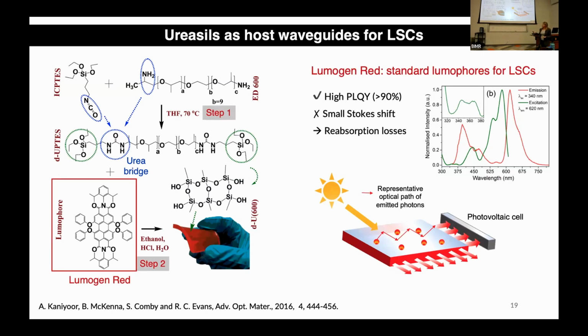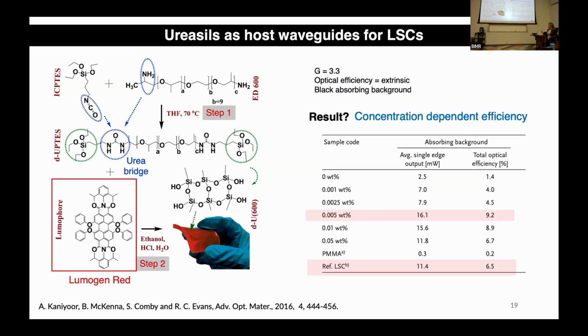And so what we wanted to do with this study was see if a ureasil could behave as a waveguide in an LSC. And that was our primary hope, and yes, it can. But what we do see is that by using Lumogen Red, of course, we get this reabsorption problem, which is concentration dependent. And so as we get to higher concentrations, we get a drop in the total efficiency. So we find 0.005 weight% gave us quite a good efficiency, 9%. And this was really good, actually. We were really surprised. This was actually competitive with anything that was out there in the state of the art. So we thought, yeah, great, ureasils are a good waveguide for this application.